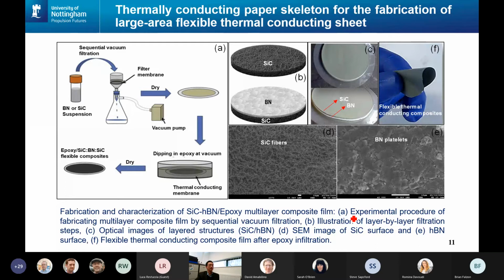We have also produced another method, thinking about large scale and flexible formats like a membrane or a film. What we do is combine a few layers of silicon carbide and boron nitride together. By this kind of design, we can reach very good thermal conductivity. At the same time, we can also offer the structure very good dielectric properties, and this is much better than commercial polyimide films. This work is still under development and we have not published, so I'm not going to report a particular date here. But if you're interested, you can send me an email.